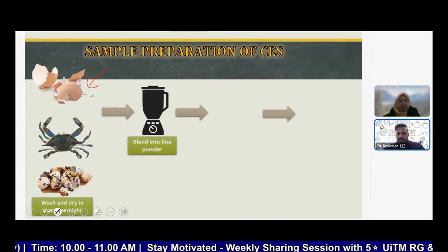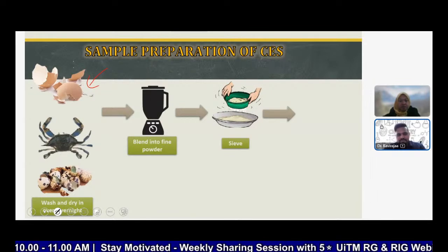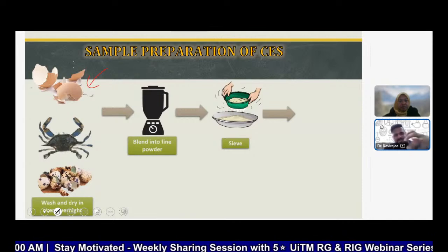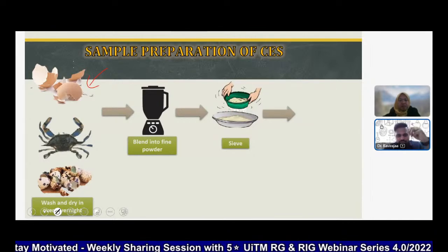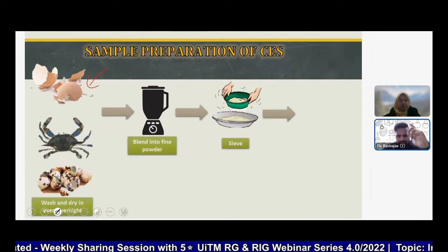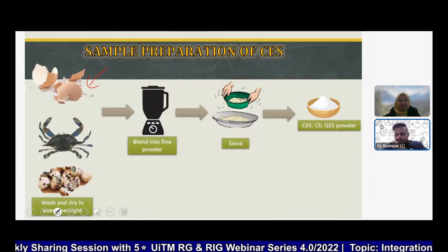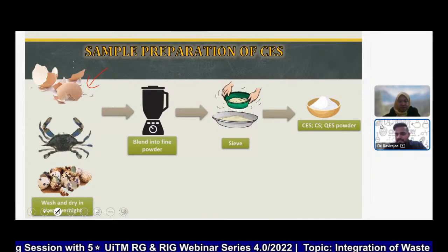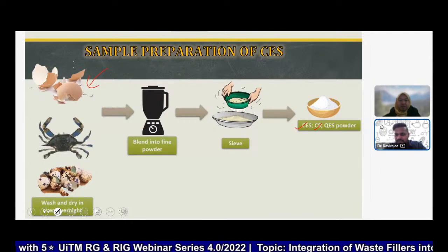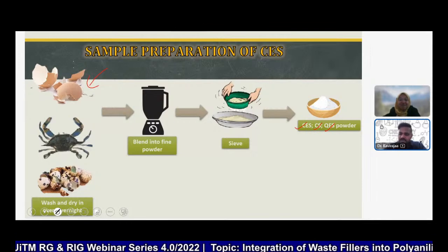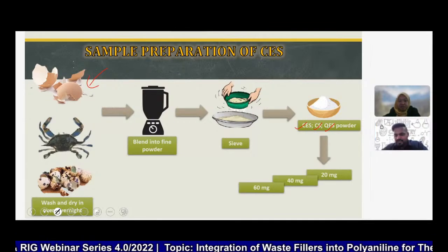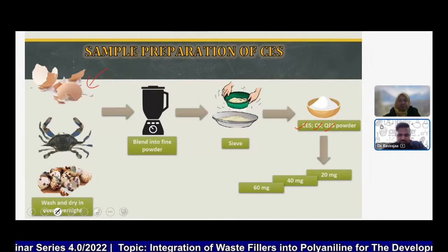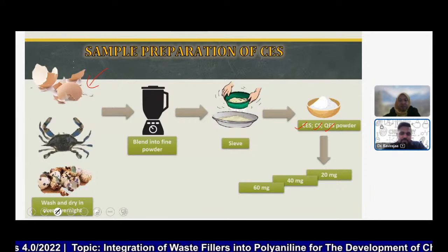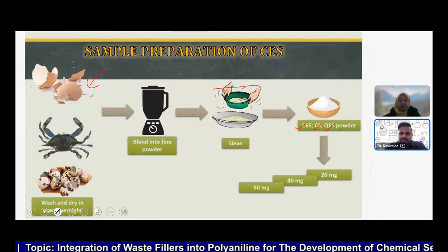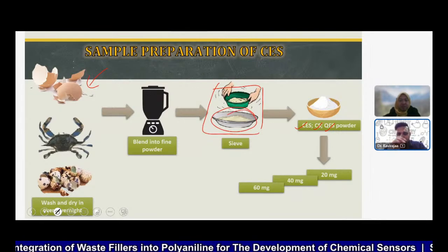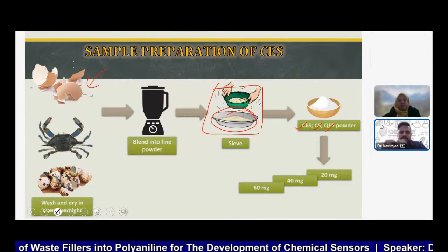And then we will grind it. We'll sieve. Why are we sieving? Because even though we grind it, due to the blade size and so on, we don't really get fine particles. So we wanted to use very fine particles. The reason is, later I'll explain why. Okay, then we have used several types of shell-based powder, like CES is chicken eggshell, CS is crab shell, QES is quail eggshell. And then we divided it into different ratios like 20, 40, 60 milligrams so that we can make the composite material. So here we sieved, and our motive is to get very fine particles, a few microns in size only, because we wanted to do ex situ polymerization.